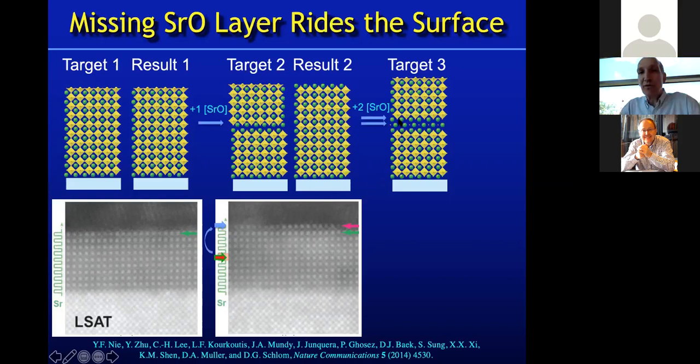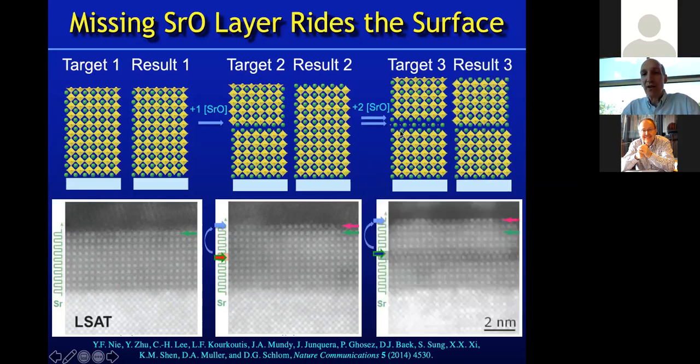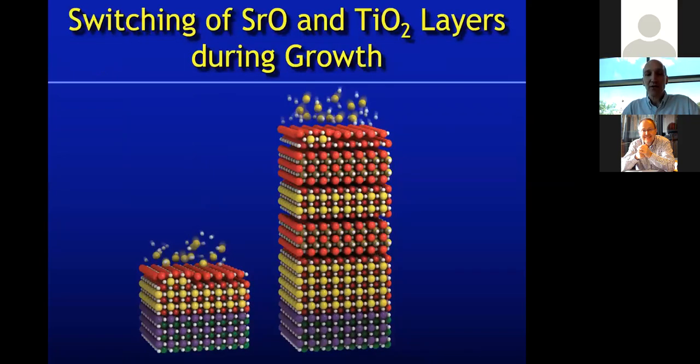What happens if you give it three layers of strontium in a row? And the answer is two of them incorporate in the structure and one ends up on the surface. So seeing how these things really grow, it's energetically favorable to have this monolayer of strontium oxide on the surface, then you can think about how it is that they really grow and overcoming